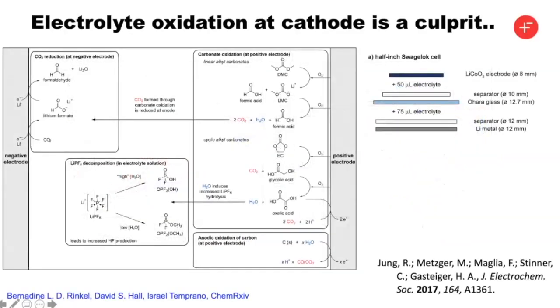And so then just to think about why, even at 4.1 volts, despite the lack of capacity loss per se of the anode and the cathode, there is lithium inventory loss due to the SEI formation. It's clear that a lot of this is coming from the electrolyte oxidation of the cathode. And of course, we're not the first to say this. There's some beautiful work by Hubert Gasteiger and his group.